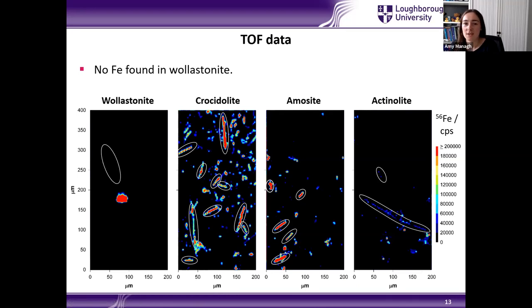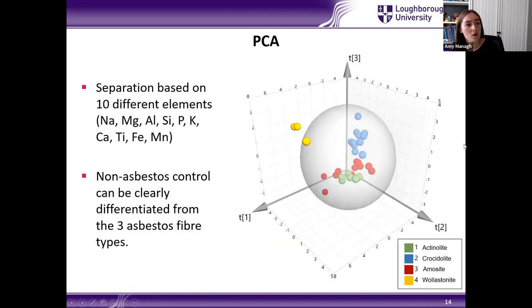So what you can probably see from this data is, in some cases, it's quite easy to visually, from our images, see differences between the different fibers. But particularly for the crocidolite and the amosite, distinguishing between these is more challenging. So we thought to ourselves, well, what could we use? What better way could we use to represent this data and to see if there are differences between the fiber types? So we used principal components analysis for this. We looked at 10 different elements within the fibers, and these were based on known constituents of the fibers and also known elements that can substitute into the fibers as well. So that's how we chose our 10.